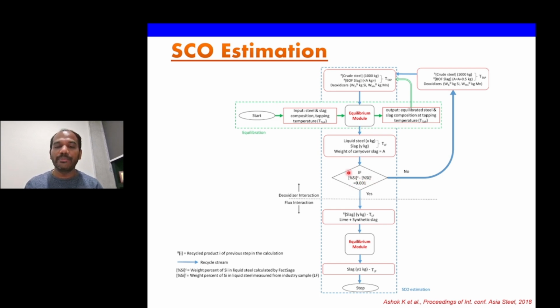So the amount of silicon that is present in the crude steel minus the silicon present initially, right? When that silicon difference is 0.001, basically we can say the equilibrium calculation is perfect and meeting the composition of the industry. Then you can go and calculate what is the exact y, that is the slag carryover, how much amount it is, and with the lime plus a synthetic slag, along with the synthetic slag, that can be recorded, right?